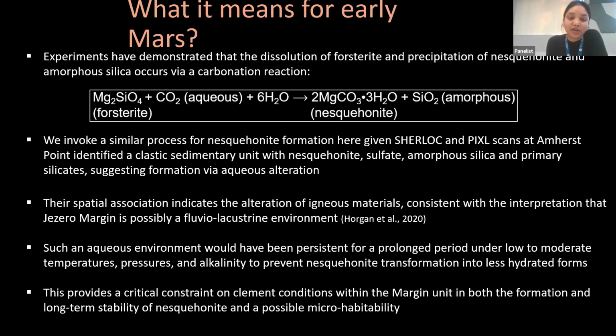So what it really means for Mars: experiments have demonstrated that the dissolution of olivine and precipitation of nesquehonite and amorphous silica occurs via the carbonation reaction that I'm showing here. So we expect a similar process for nesquehonite formation on Mars, possibly, given that SHERLOC and PIXL scans of Amherst Point identified a clastic sedimentary unit with deposition of nesquehonite, sulfate, amorphous silica, and primary silicates, suggesting formation via aqueous alteration.